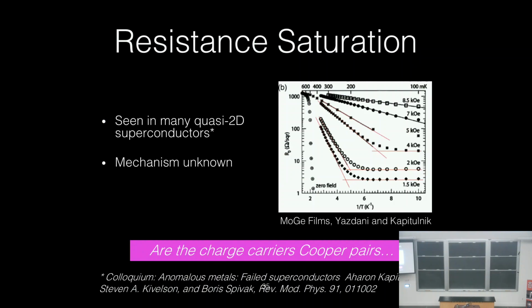But let me first tell you that a lot of people have been working on this. Here's a paper that came from the late 90s on molybdenum germanium films. There is a recent paper on niobium diselenide films in a group that Leo Lee was working in, and they were seeing these metallic-like behaviors at low temperatures. We don't know what the mechanism is, but we think we've done an experiment that's going to help at least cut away some of the ideas.